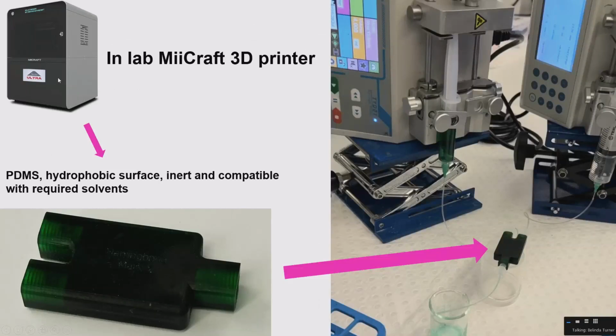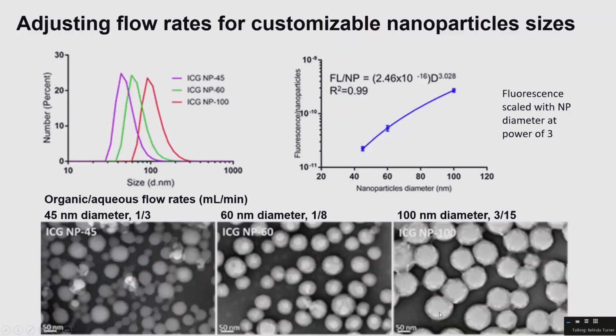So we're lucky enough to have a MiiCraft 3D printer in the lab, so we print these devices in-house. They are made out of PDMS, which is great for this application as it's largely inert and compatible with the required solvents that we need, and it has a hydrophobic surface, which means that the particles won't interact and accumulate along the device, hopefully. So this is our typical setup in the lab. We've got 2 syringe pumps, which pump in, and then it's just eluted out.